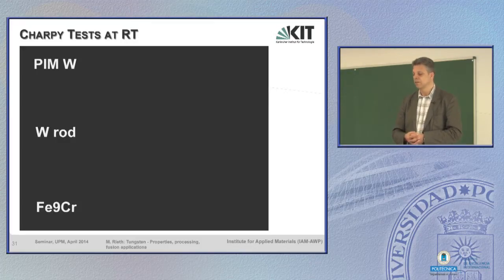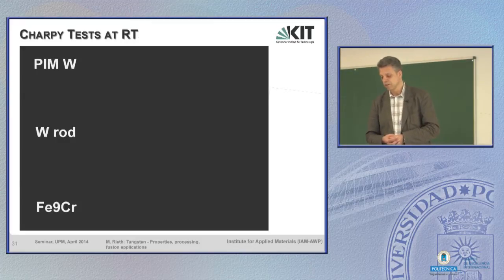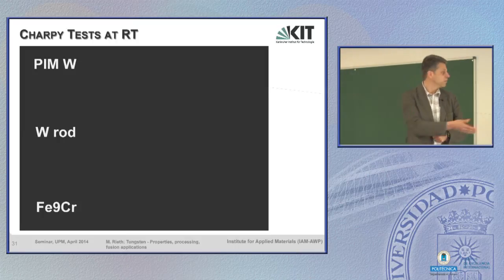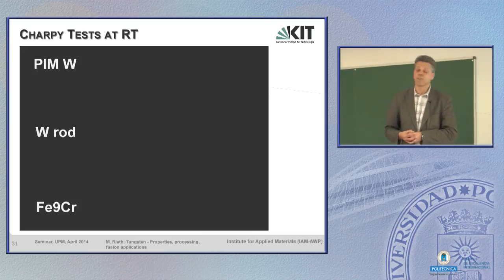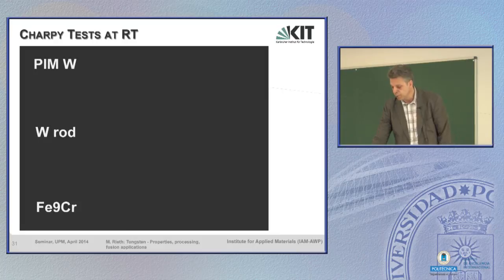Again, a Charpy impact test of tungsten rod in the middle and sintered tungsten on the top. And on the bottom, this is compared to steel, all at room temperature. We would like to have the fracture behavior as we can observe it in steel at the bottom.